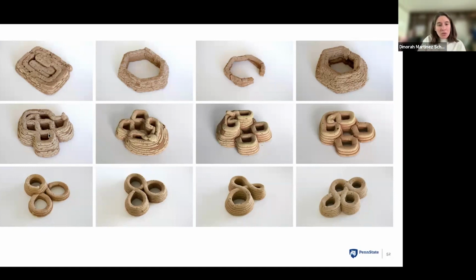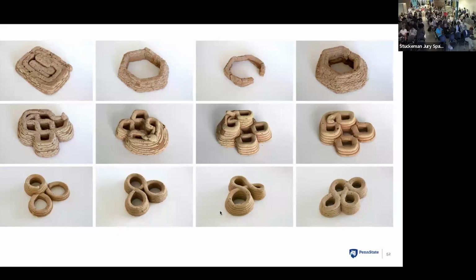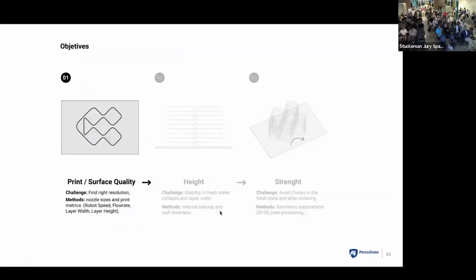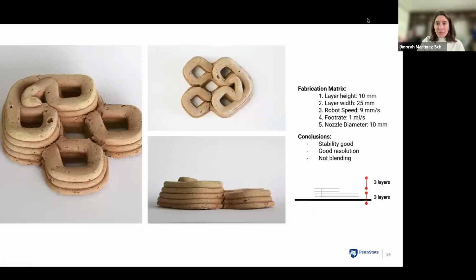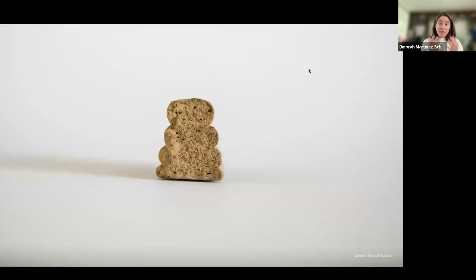So I started to do a square infill, but then it didn't work very well. So I changed it to a circular geometry. One of the first objectives of this research was, how can I get the best quality of printing? As you can see in the fabrication matrix, you can see the layer height, the layer width, the robot speed, the flow rate, and I started to change these parameters to get the best result. Then I found this. This is how the material started to behave and started to work.